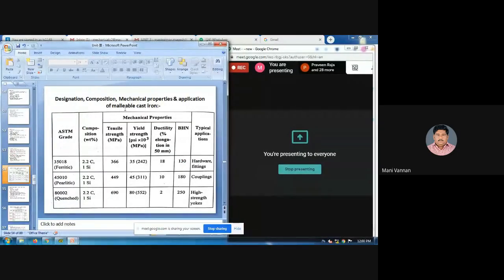The designation, composition, mechanical properties and application of malleable cast. This is the ASTM grade. Okay, 35018 for ferritic, 45010 for pearlitic, 80002 for quenched. Composition in weight percentage, 2.2 percent of carbon, 1 percent of silicon, for each grade. Mechanical properties. Tensile strength, megapascal: 366 megapascal, 449 megapascal, 690 megapascal.